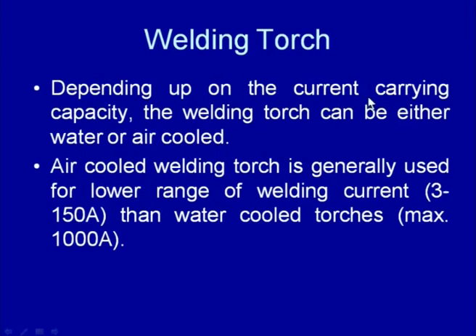Depending upon the current carrying capacity, the welding torch can be either water cooled or air cooled. Air cooled welding torches are generally used for the low current range, while water cooled torches are used for the high current range. Maximum they can go as high as up to 1000 amperes. It is common to work with the GTA processes up to 200 or 300 or 350 amperes.